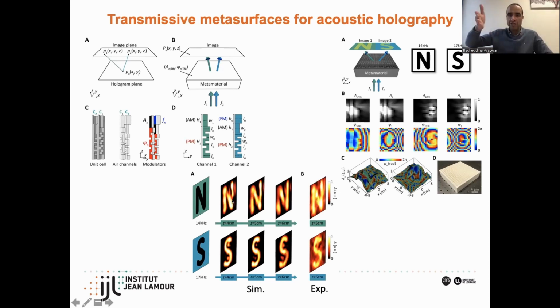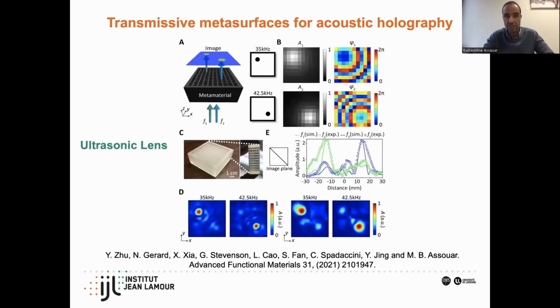We made the simulation at different distances from the metamaterial plane to the hologram plane, or hologram projection, and we found that at 5 centimeters we can get very good results. So we reproduced that experimentally, and we can project by transmission 2 different holograms based on 1 metasurface. We can do that for more frequencies, but it's a little bit more complicated, because the unit cell should be a little bit more complex to do, but it's doable.